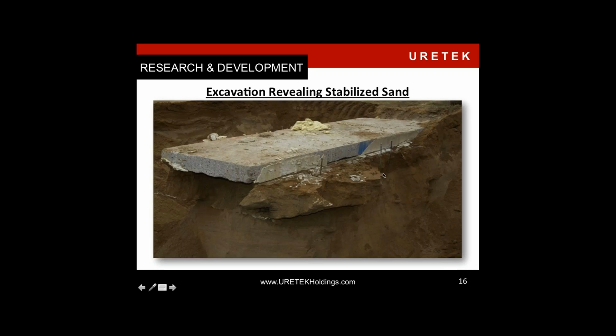We were able to inject around the perimeter of this slab, creating a grout curtain wall, if you will. So then when we went through the slab in the center and injected, the material had confinement, because remember, as I mentioned earlier, HDP will expand in the path of least resistance. We ultimately want to have it up against this slab stabilizing. So because we created this grout curtain wall, we have confinement of the material on the interior soils so that it densifies by consuming the least amount of material.